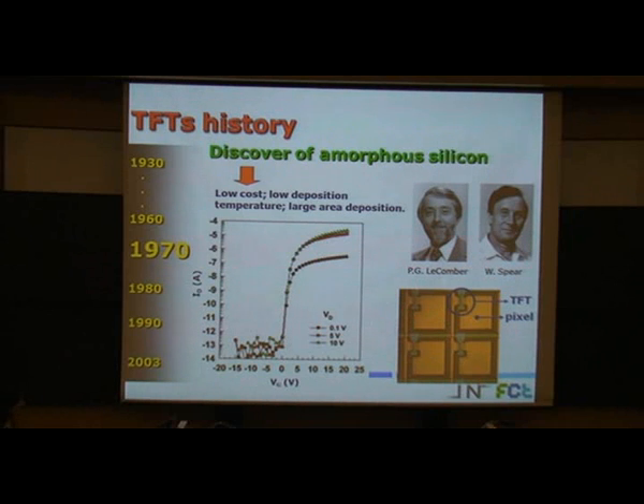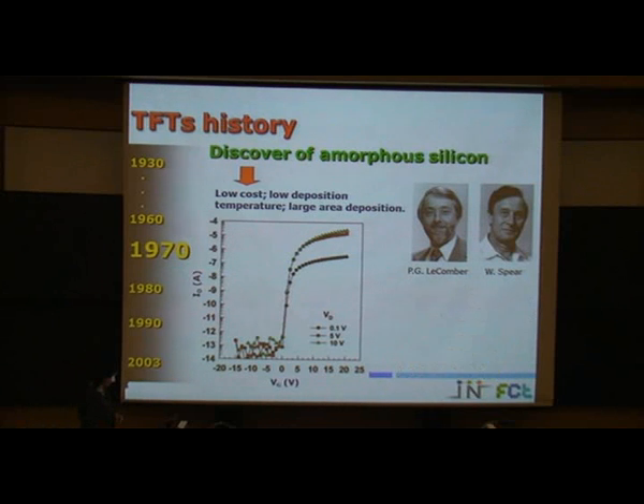With the invention of amorphous silicon, and the possibility to deposit this material on large surfaces at low temperature, all this technology revolutionized the display industry. Even today, all the displays that we are using are based on amorphous silicon TFTs, the TFTs inside this screen. This is a picture with 4 pixels, and here is the TFT that switches the pixel of the display. Of course, the devices work well, and we are still using this type of transistor in our displays, but the material presents a drawback. The mobility is quite low, around 1 square centimeter per volt per second.